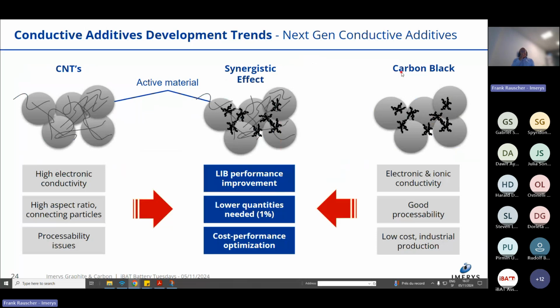We work on solutions where we combine carbon black with CNT. Why? Because we think, and we also have data that show that, and it's not just us, you also see that published in literature, that there is a synergistic effect. Carbon black, amorphous conductive carbon black, has good electronic conductivity, but is also very, very good at lithium-ion conductivity, where CNTs are not good. You have good processability, you have the quantities available, it's a lower cost material, you have industrial scale production available, and if you combine that with CNTs, you basically get a better conductive additive.